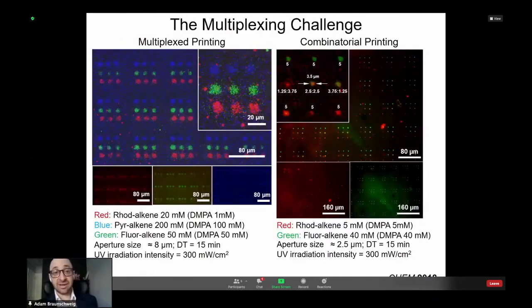And then here you can see that we can, in fact, put different molecules on the surface in close proximity. We can either serially introduce different colors. So this is the compilation of the 3 different fluorescent channels shown below. You see we could print the blue, the green, and the red. Alternatively, we can capitalize on the microfluidics to mix the compounds in different ratios. So the numbers here correspond to the flow rates in microliters per minute. These were printed with 5 microliters per minute of just the green dye. Here were the different mixtures of green and red, and then here's just red.